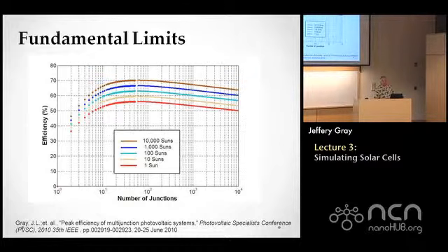But then you start getting into the fact that you keep diminishing the current, and since it's a current-voltage product, it tends to flatten out. And it turns out the flat part is somewhere around 55 junctions. Now, no one is even contemplating 55 junction solar PV arrays right now, although there's a company called EMCORE in Albuquerque. They're right now working on a 6 junction PV system.